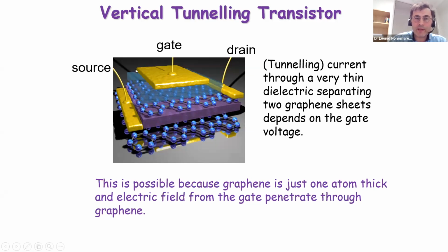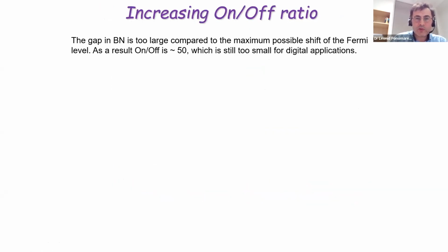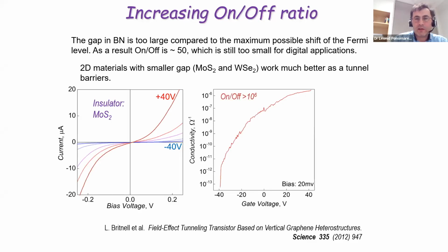What is interesting is that if we place a gate electrode and apply an electric field, this field penetrates one of the graphene layers because it's so thin, and changes the properties of the tunneling barrier. And the current can change a lot. That was tried first with boron nitride. We increased the on-off ratio to 50, which was better, but not so great. But then we started to use different materials like molybdenum disulfide or tungsten diselenide. With molybdenum disulfide, as shown here, you see examples of